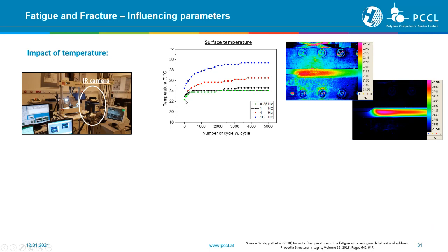As you see here, it is 22 to 24 for the lowest frequency, but we are here from roughly 24 up to nearly 30 for 10 Hertz. At the end, this is only for a pure shear specimen, and the pure shear specimen is a little bit thinner compared to the Dumbbell specimen, which has a diameter of roughly 12 millimeter. Here we have a thickness of 4 millimeter or 6 millimeter, which makes a big difference.